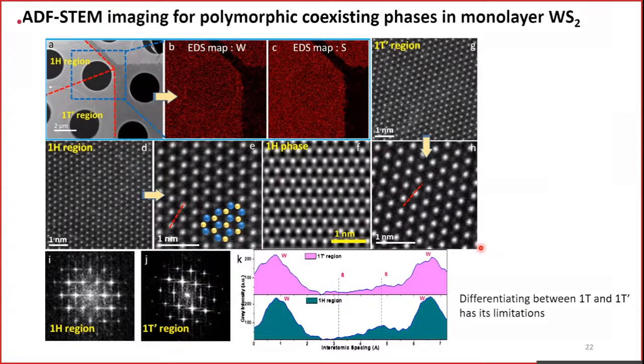Again, in order to get a clear confirmation of the phases, we have done atomic resolution annular dark field STEM imaging from the same flake, on the different triangles that we discussed earlier. We can again clearly see the small distortion that I talked about. We get some indication of sulfur. As I said earlier, if it is a 1H phase, you will get only one sulfur position, whereas in the 1T prime, you have a small distortion in the sulfur that we are able to capture in the aberration corrected